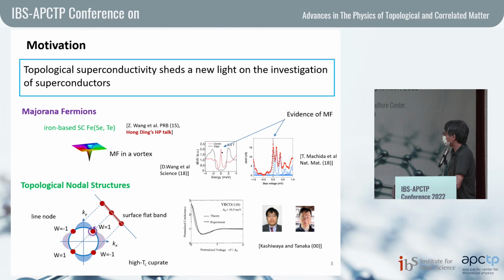mode. And we also know that nodal superconductors also have very nice topological natures. For example, if you consider the high Tc cuprate, we have line nodes, and they have their own topological numbers. Correspondingly, if you create the surface in this direction, we can obtain the surface flat band because of these topological numbers. And actually, the presence of the surface flat band has been observed by using the tunnel conductance measurement.